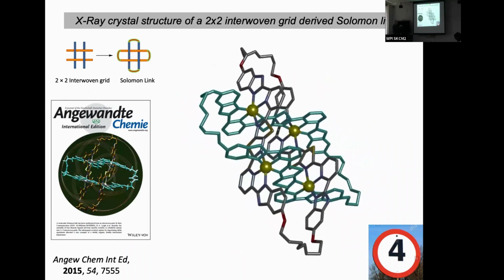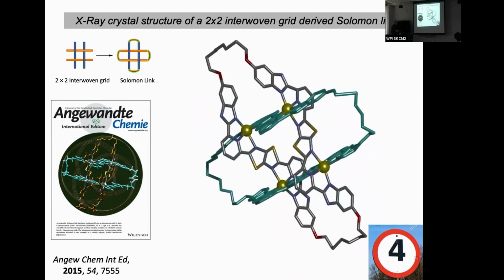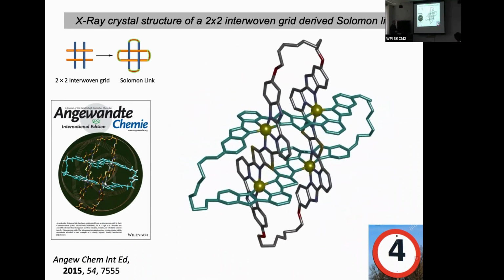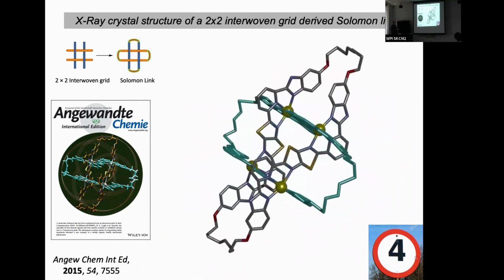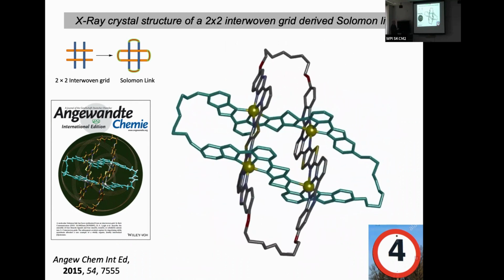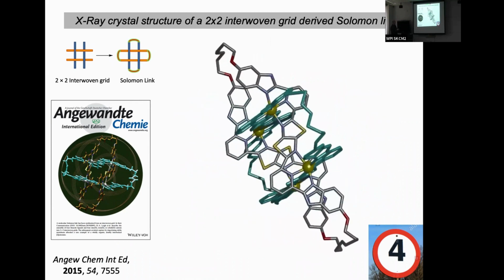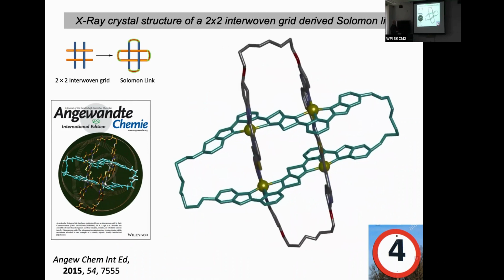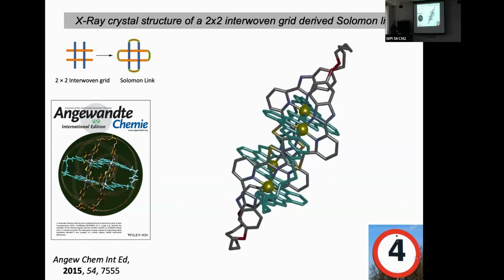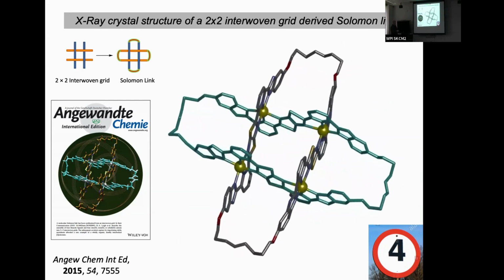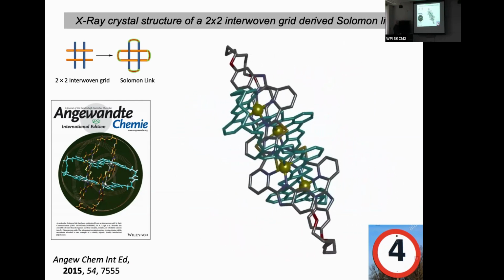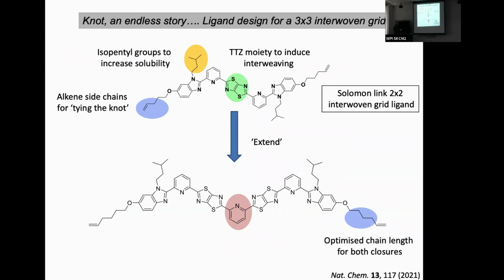And the reason for that is that entangling rigid strands puts strain on the molecules and stops them happening. So we first set up these studies with a 2x2 grid and closing the end groups there to form a Solomon link, a doubly interlocked catenane. This is the X-ray crystal structure of a molecule that we made with a particular ligand strand that forms these nice over-under entanglements. So we figured that what we needed to do was to just extend this ligand strand, to add extra units to go from a 2x2 binding site to a 3x3 system. So we just extended it and added an extra group here.